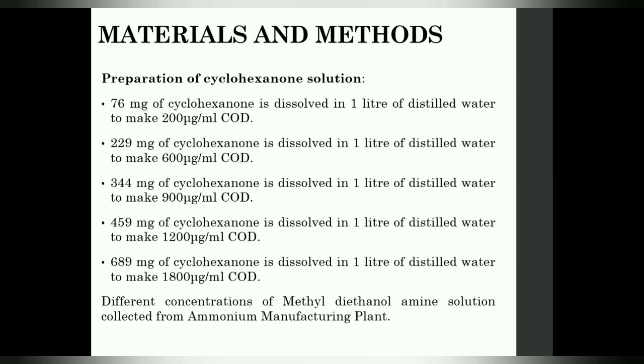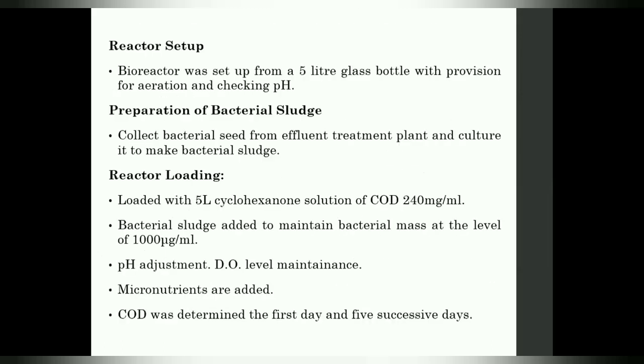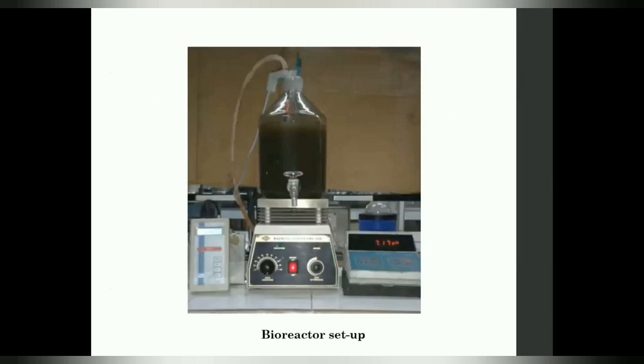So this is how we prepared the cyclohexanone solution in various concentrations. A reactor was set up. Since the reactors available there were of 50 liters and higher, we had to set up a bioreactor. As you see in the diagram, it has a pH control, then the treated effluent in the flask, along with that the cylinder. This cylinder is 5 liter. We have a provision for aeration, and also for checking pH. Similarly, everything was manually controlled.